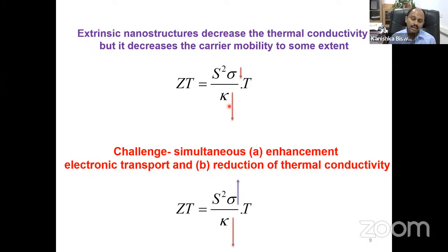So can we think of a new approach where we see an enhancement of the electronic conductivity and a decrease in the lattice thermal conductivity at the same time? This grand challenge was there in this field for almost 10 to 15 years. So, enhancement of the electronic transport and reduction of the thermal conductivity at the same time. In that direction, we have been working for almost 10-11 years, since I started my group at JNCASR in 2012.